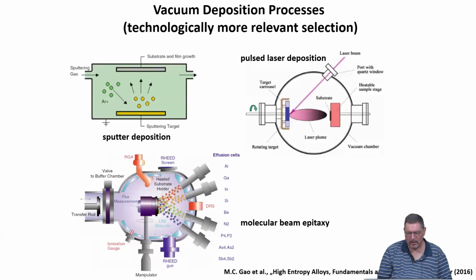If we want to go for coatings, obviously there is a range of methods, and industrially more relevant are these three: sputter deposition. So we have talked about sputtering already, right? So you have ions, in this case often argon ions are used, that impact on the surface. This is your target. Atoms are sputtered off that target, and then they are deposited on the substrate, which you normally control in terms of its temperature and so on. And so you form films. You can also use pulsed laser deposition by again using a laser to evaporate from a target and then deposit on the substrate. Or you could thermally evaporate different materials in these effusion cells, Knudsen cells, and then basically have a small pinhole so that you can direct a beam onto a substrate, and then depending on how many sources you have, you basically can mix different alloys.